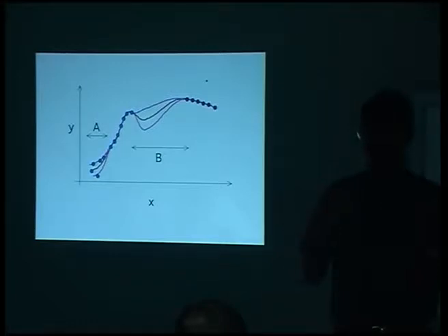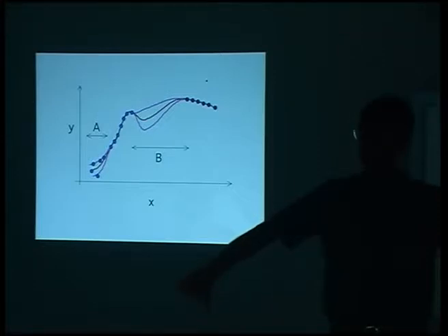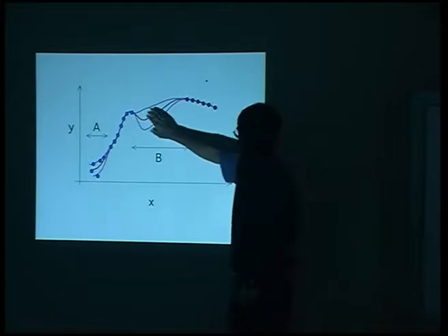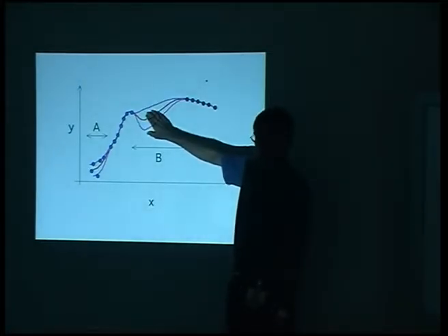Whereas in linear regression, you can specify the range over which your data exists simply by tabulating the minimum and maximum values. That's no longer possible in a nonlinear function, because say if I have a range of carbon concentration from 0.1 to 0.2 over here, I might have a different range where the manganese concentration is different. Okay? So it's impossible to say that I've created a model within this domain of experimental data, because the range will vary according to where you do the calculation, and this is a method which tells you how dangerous a territory you are in. So this is extremely important, and not all neural networks do this.